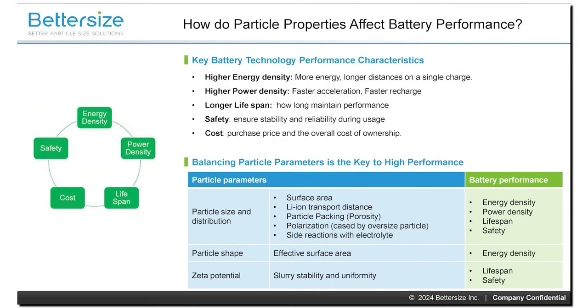These particle properties have significant impact on the battery performance due to their role in determining the efficiency, capacity, cycle life, and safety of the battery. And here's how various particle properties influence battery performance. Particle size affects electrode packing density, surface area, and ion diffusion rates. Smaller particles enhance capacity. However, excessively small particles can lead to increased side reactions and loss of active material, affecting battery stability and cycle life.